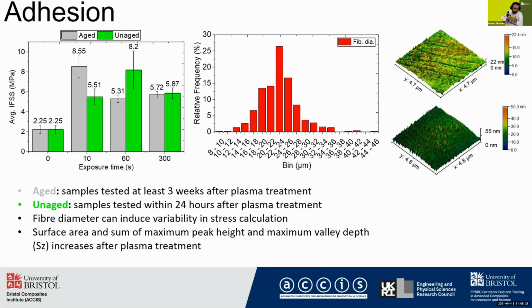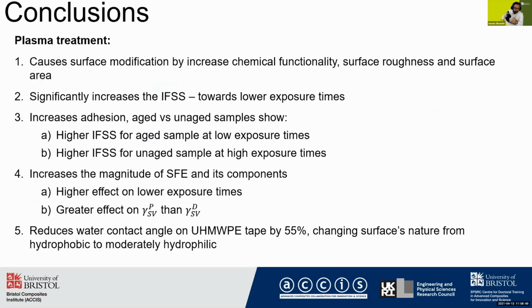We also know that plasma treatment increases the surface roughness, and that could lead to the increase in the adhesion. However, it is to be noted that this testing method assumes that the stress is constant throughout the interface, and parameters such as fiber diameter variability can introduce variability into the stress calculations.